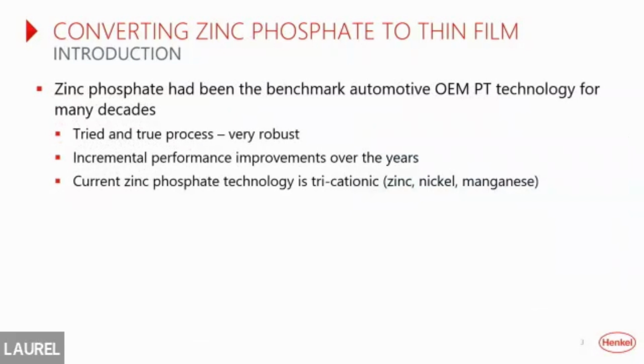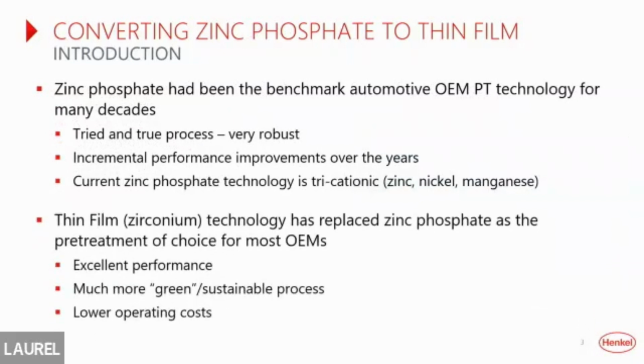And over the years, there have been incremental performance improvements with different ions that are used. At one point it was dicationic, now it's tricationic, and improvements in the surface conditioner have even boosted the already excellent performance. As far as zirconium goes, it also has excellent performance, and it has really become the choice for most OEMs. There's a few OEMs that still have not stuck their toe in the water of zirconium, but they're moving fairly quickly to do that. It is certainly a much more green technology, very sustainable compared to zinc phosphate, and lower operating costs. For those of you who are using it, that's very clear at this point.